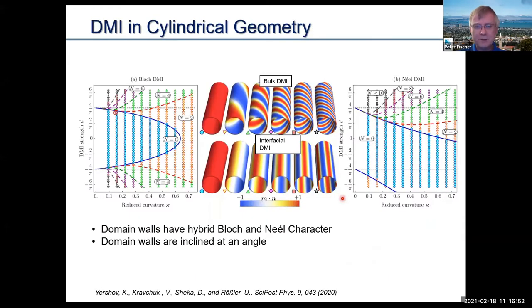And there was just a recent paper, for those of you interested, where they found, for instance, that a domain wall, which in a planar geometry would be pretty straightforward, in a cylindrical geometry all of a sudden would look very different. For instance, they have a character that is both of a Bloch as well as a Néel type. It's a mixture of those. And interestingly, these domain walls are also inclined if you have something like a shell or a boundary around a nanowire that is at an angle like this one here. And the angle itself, as shown by these graphs here, is almost a measure of this mixing of Bloch and Néel character. So this is, I think, again, an opportunity and an avenue to study curvilinear magnetism in these new things.